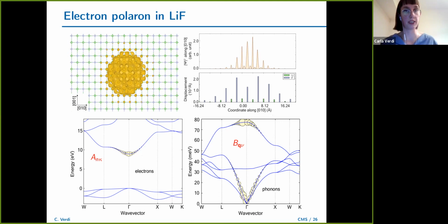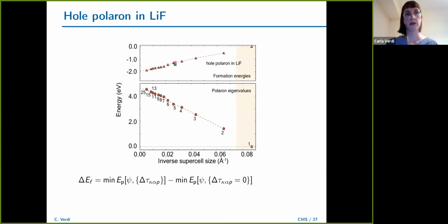And this is what you would expect for simple models of lithium fluoride, where you would expect that this is the physics, this is what's going on. But actually, it's not just that, because there is also sizable interaction with acoustic phonons, which you would not expect, and you would not be able to quantify if you used a simple model. This is instead the case of the hole polaron in lithium fluoride.